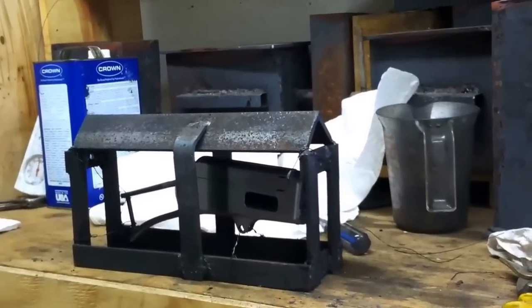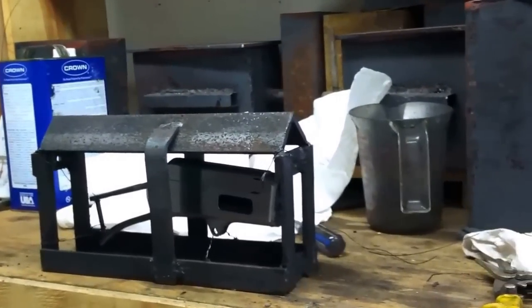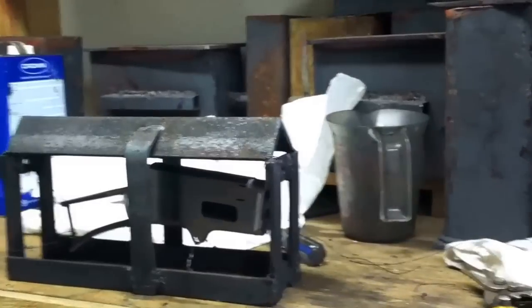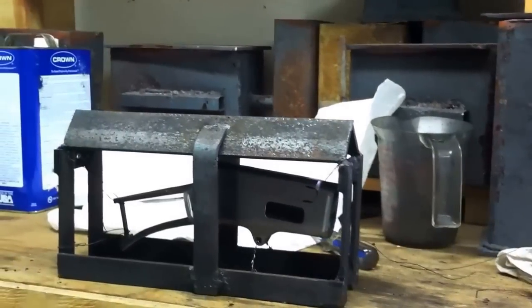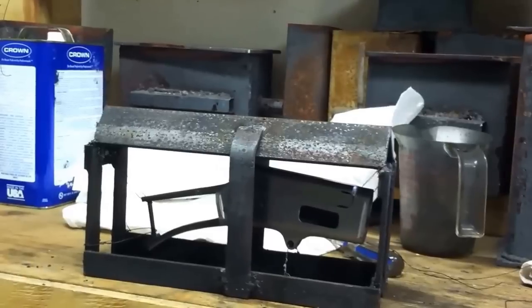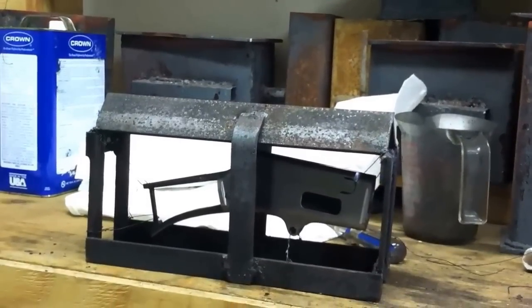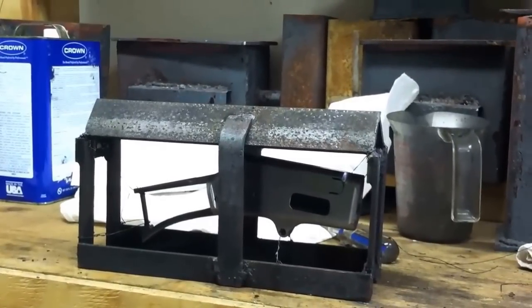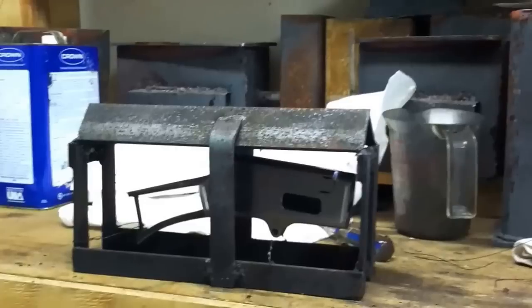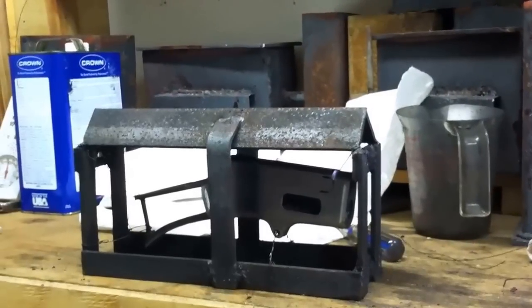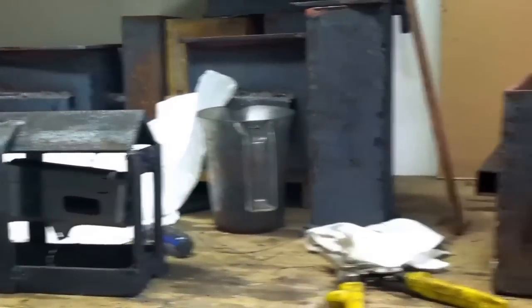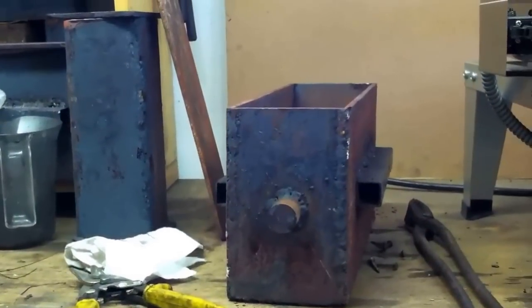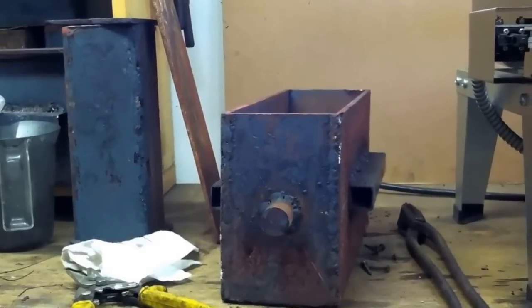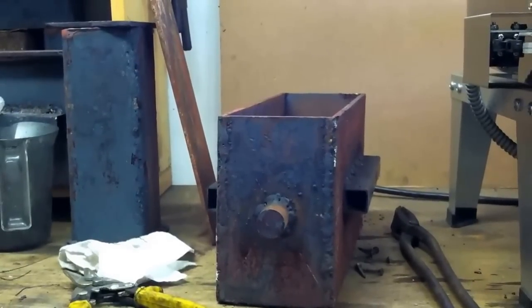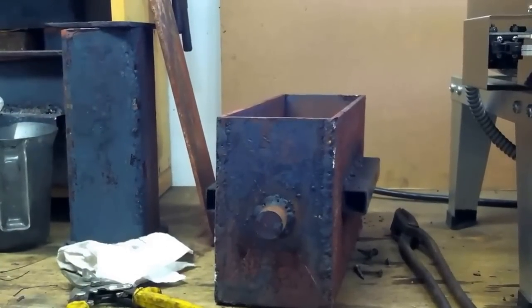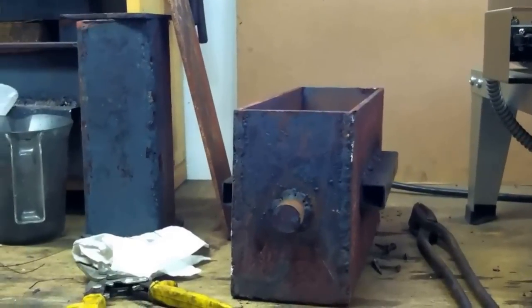Okay, what we have here is the receiver, lower tang, and the bolt wired inside this cage fixture. We've used a small gauge black iron wire to attach all these pieces in there. They're going to be suspended in that cage. The cage will then go into the crucible and be packed with a mixture of bone and wood charcoal, and then go into the heat treat oven.